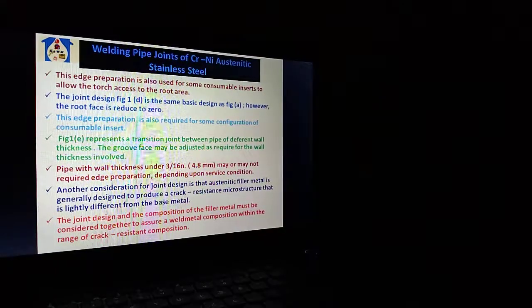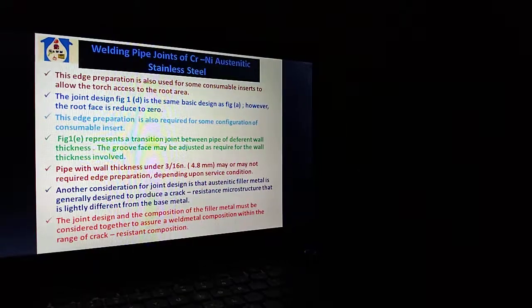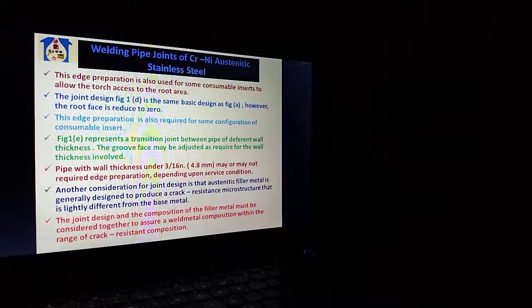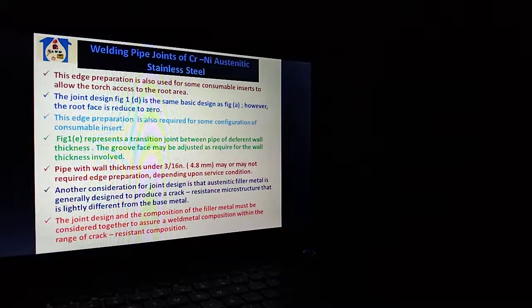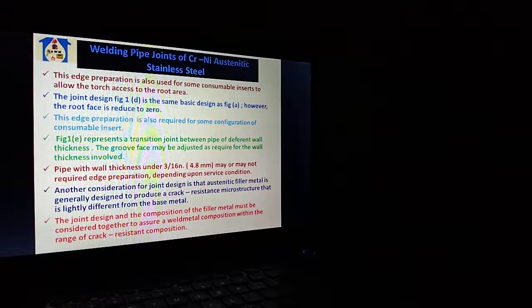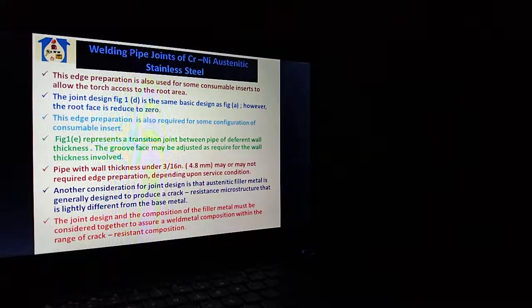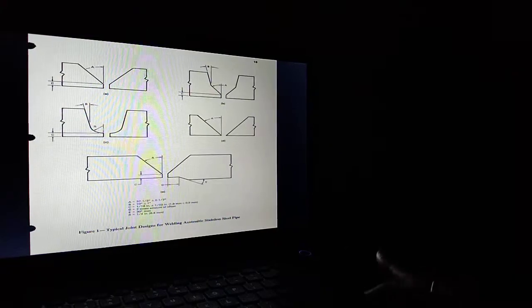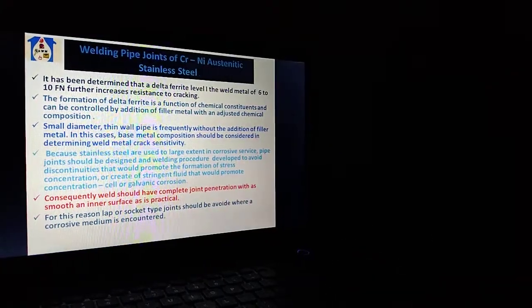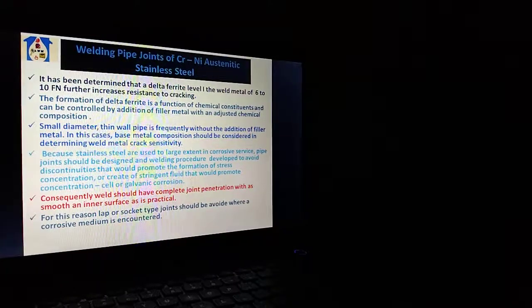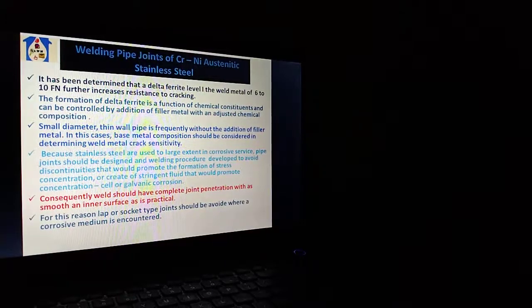Another consideration for joint design is that austenitic filler metal is generally designed to produce a crack resistant microstructure that is slightly different from the base metal. The joint design and the composition of the filler metal must be considered together to assure the weld metal composition within the range of crack resistant composition. Configuration of joints. It has been determined that a delta ferrite level in the weld metal of 6 to 10 FN, FN meaning ferrite number, further increases resistance to cracking.